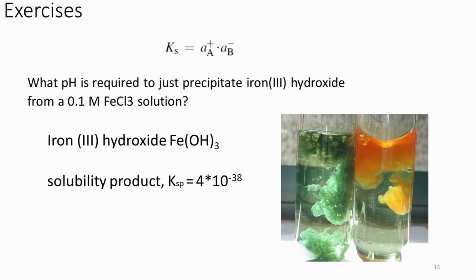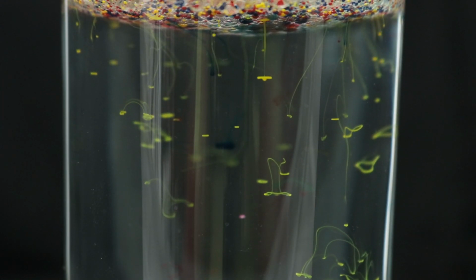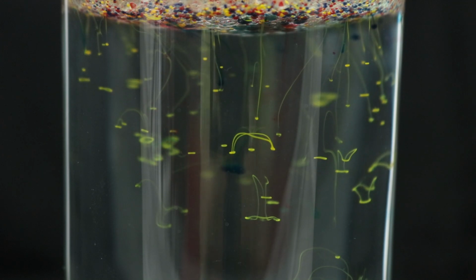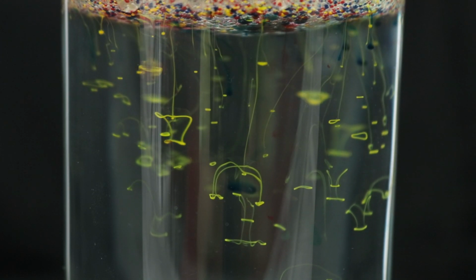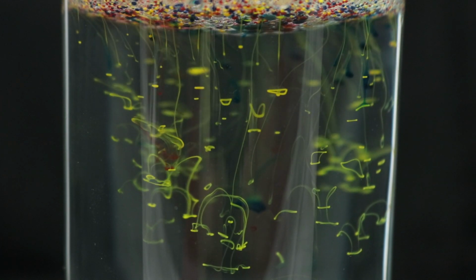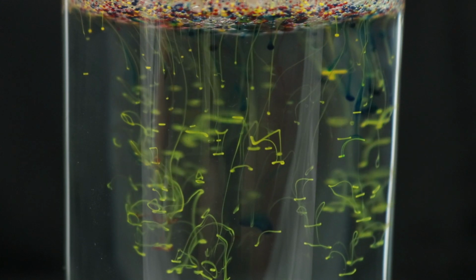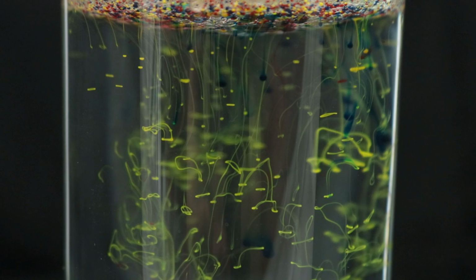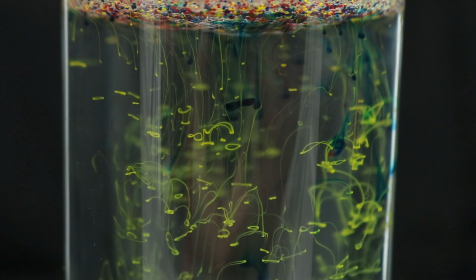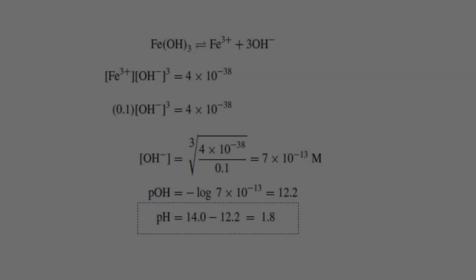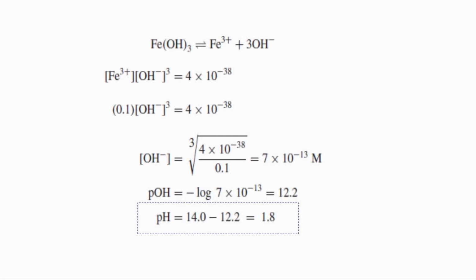Let's do an exercise. What pH is required to just precipitate iron 3 hydroxide from a 0.1 molar iron chloride solution? We see that iron 3 hydroxide precipitates in acid solution when the pH just exceeds 1.8.